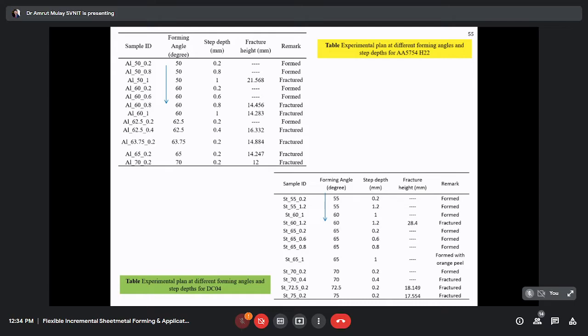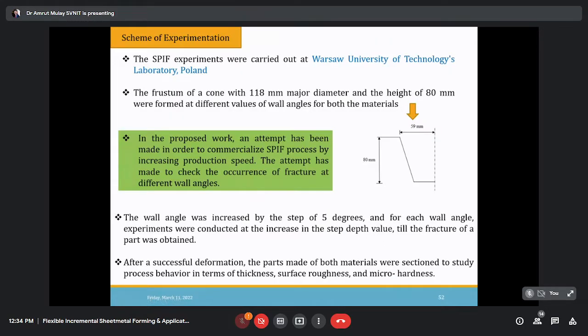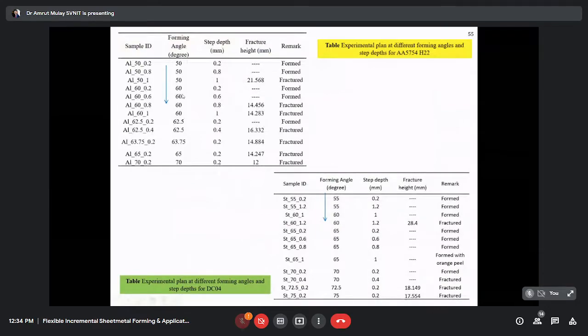Now you can see, very interestingly, at the initial time 50 underscore 0.2 it is formed, and 50 underscore 0.8 we performed, it is formed. The geometry is shown here. You can see the geometry is like this. But when I take forming angle of 50, step depth of 1, it is fractured. And the fracture depth is 21.568. It means that when anyone wants to form using the CNC machine at a forming angle of 50, the maximum step depth he can use is 0.8.